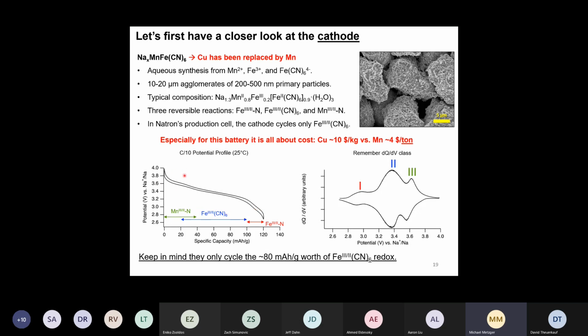The high voltage capacities are associated with the manganese 2+, 3+ redox. If you want to go to that higher voltage, then this capacity you get at moderate voltages here is from the iron 2+, 3+. And then the iron that is coordinated with the nitrogen, if that undergoes a 2+, 3+ redox, then you get lower voltage capacity, let's say here. If you use all redox couples that are available in the material, you can extract 120 milliamp hours per gram from this material. Only the iron hexacyanoferrate 2+, 3+ redox here in the middle would give you about 80 milliamp hours per gram.